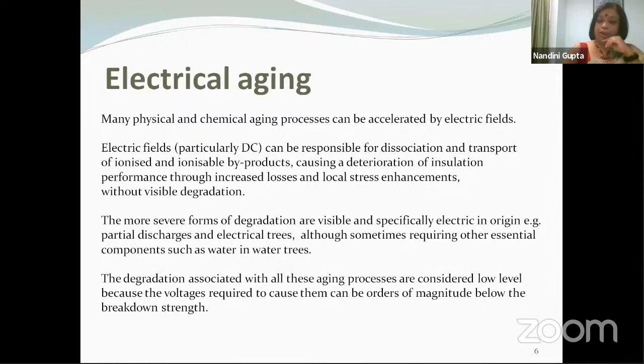But also because they might be accelerated and they may cause local stress enhancement in a manner similar to what I have discussed yesterday in case of partial discharges. So I will not discuss that. But what I'm trying to say is that when you have electric stresses on a material, there are dissociation and transport mechanisms already going on, which you will not see, and they are contributing to the degradation, which you will not be able to see. It is happening all the time, just like we are aging all the time, even though we may not see signs on the go. Without any visible degradation, the material continues to degrade.